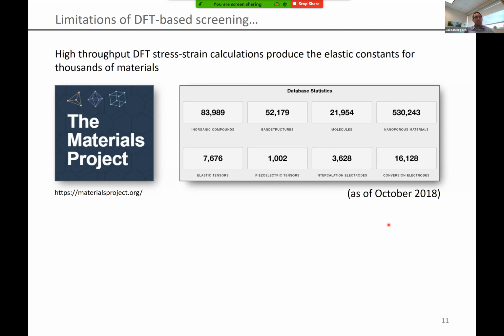So you need the elastic tensors in order to get a material's bulk and shear modulus. And so we started to take a look a little bit closer at using things like elastic tensors to do some large scale material screening for materials that might have really high hardness.